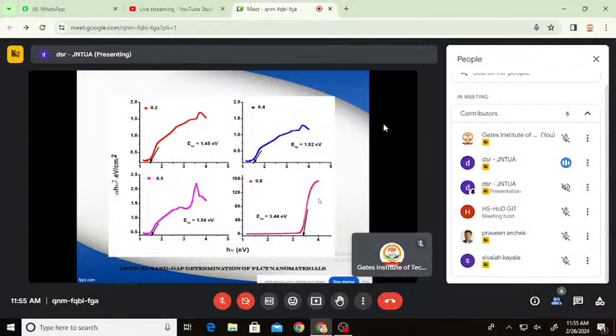The color of the samples is also found to be changed. The first two samples, that is Z equals 0.2 and 0.4, are found to be light brown in color, whereas the third one, that is for the Z equals 0.6 combination, is found to be thick brown, while the last sample, Z equals 0.8, is found to be pure white. This confirmed that